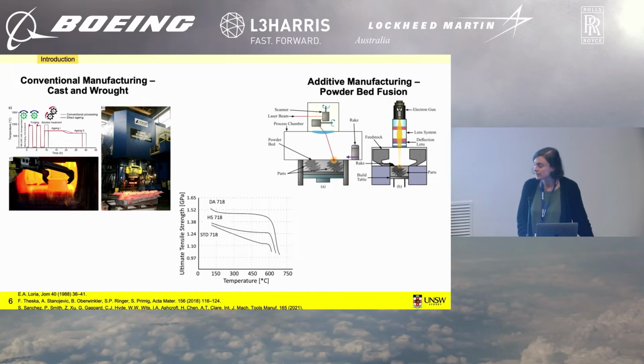But what we are ultimately wanting to achieve is to shift these curves to higher temperatures and higher strength. And you can do so by getting the best out of existing materials and by designing new materials. So this is an example from my research on alloy 718, where we work a lot on a forging schedule that's called DA, or direct aging, that achieves the highest strength properties.